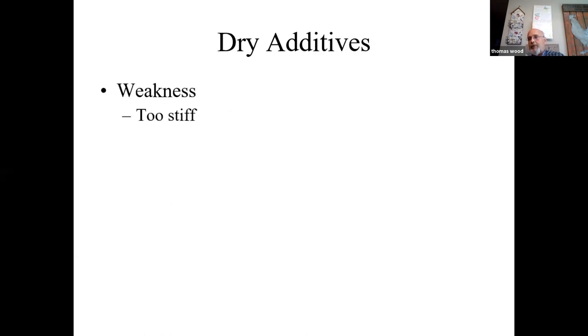Weaknesses: it can be too stiff. If you're using cement, you need to stay with your 7-day strength on stabilized full depth reclamation, which needs to be under 300 PSI in 7 days. And I'm guessing you need to be in the same range with CIR. If you get it too stiff, it's going to crack. You're going to get a crack pattern that's hard to get out.